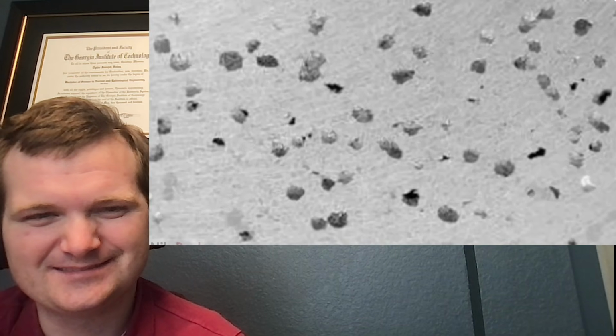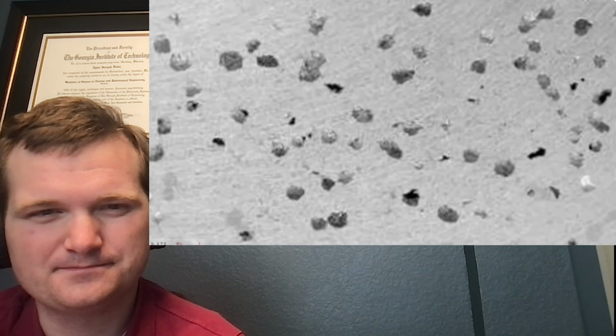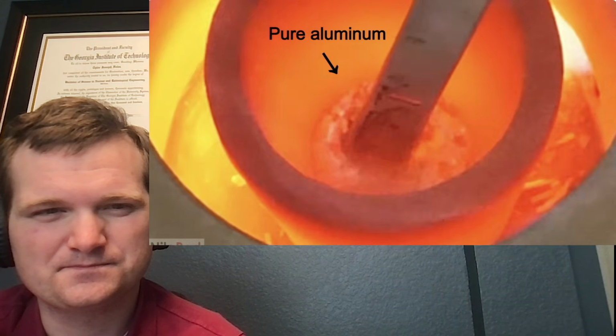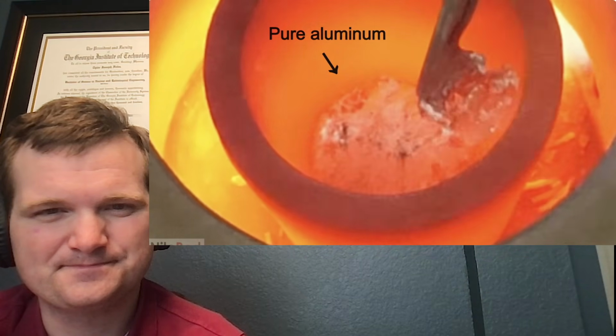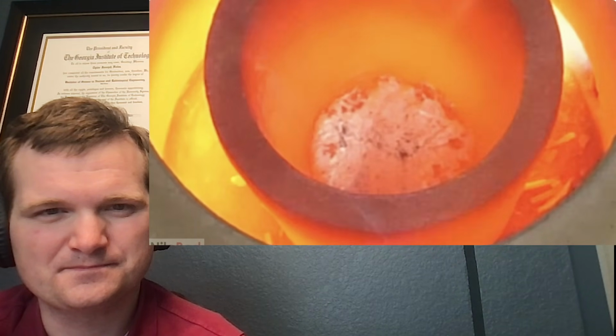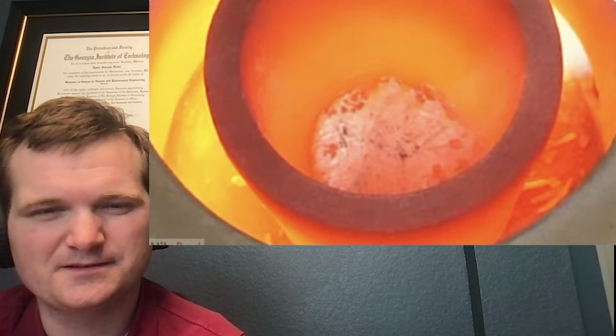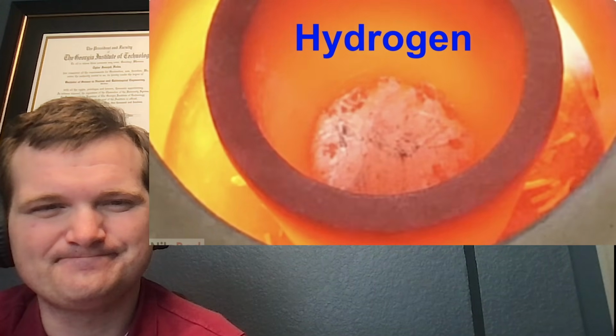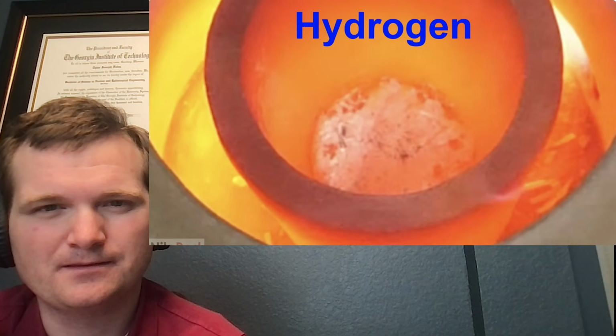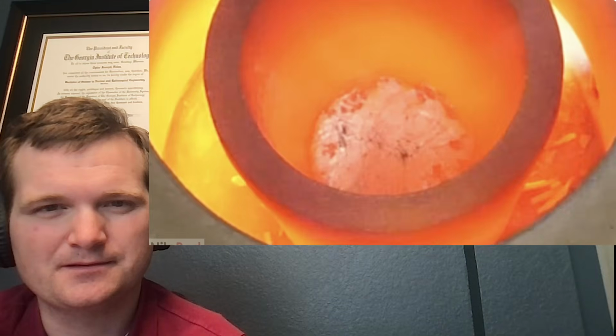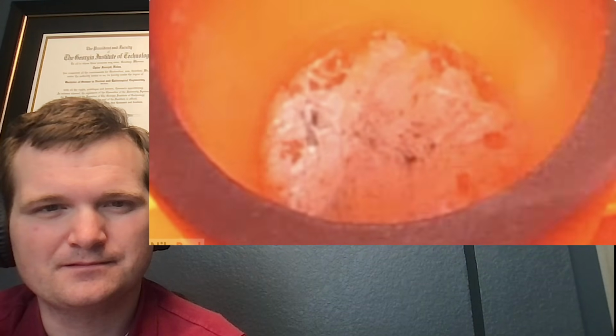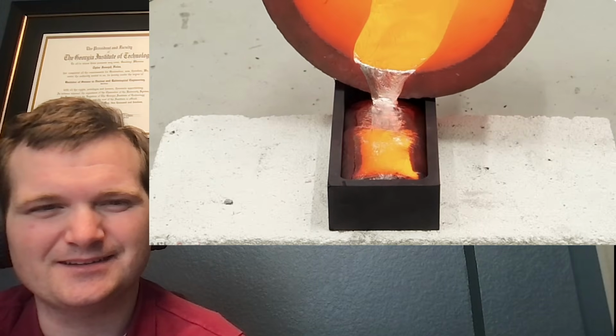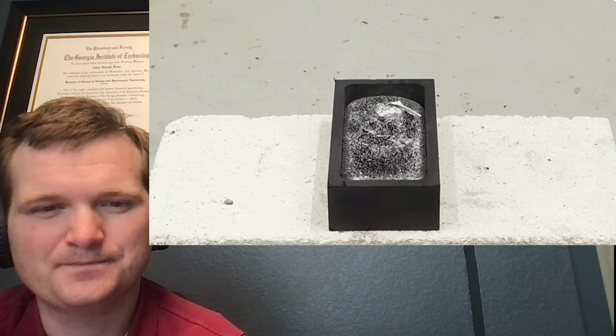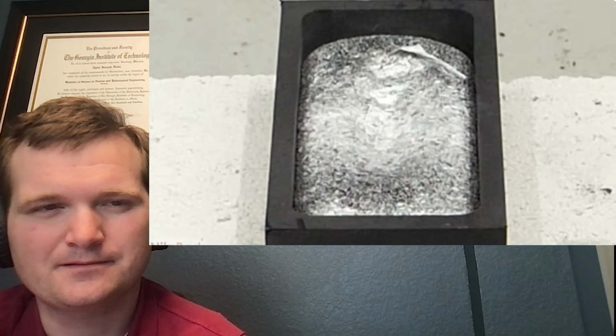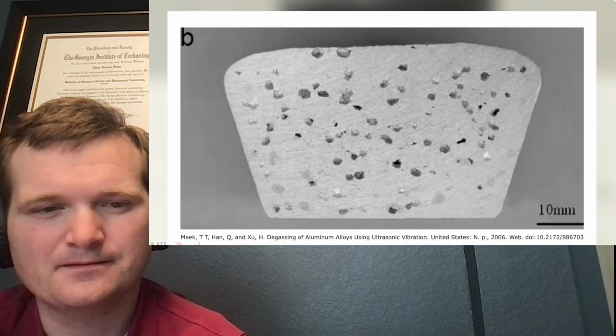All of the dark spots were small holes, just like what I was seeing with the purple gold, and apparently, this was mostly just caused by moisture in the air. This is because when aluminum is molten, it's able to react with the moisture, which then causes it to form some of those crusty oxides like we saw before, as well as some hydrogen gas. I always kind of assumed that all of this hydrogen then just floated away, but apparently, a lot of it actually gets dissolved into the molten aluminum. Then, as the aluminum cools, the solubility of the hydrogen slowly decreases, and right around the time that the aluminum is solidifying, it all gets kicked out as a bunch of bubbles.